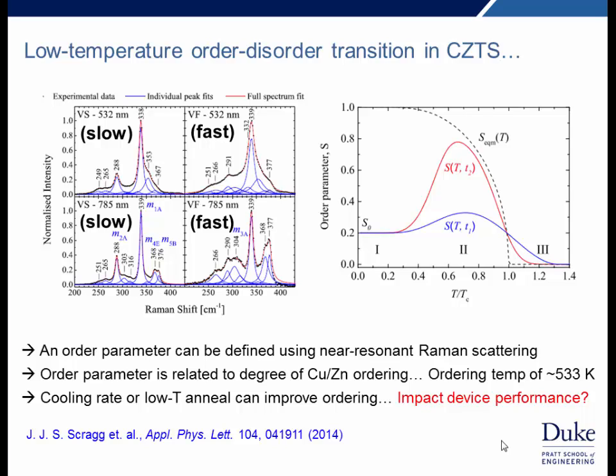The first is some work from the Angstrom labs and others, where they were looking at first a way of characterizing the disorder. And in this particular case, it's characterized using near-resonant Raman scattering. One can define an order parameter, depending on the intensity of certain peaks in this resonant Raman scattering spectra, which characterizes the degree of copper-zinc ordering. And what they distinguished is that there's an ordering temperature at around 530 Kelvin. And below this temperature, the copper and zinc start to order.